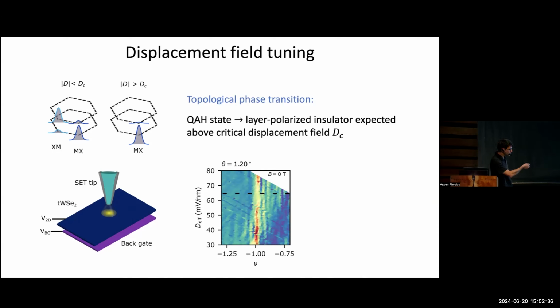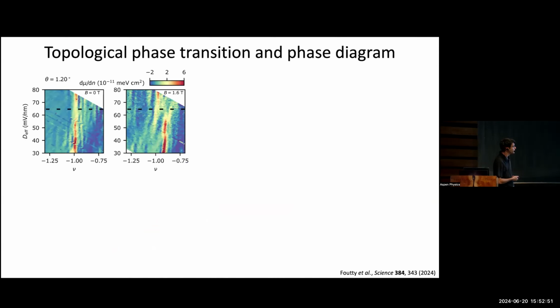So here, this is a picture at nu equals 1. As you increase the displacement field, this incompressible state gets weaker. And then past the critical field, it starts strengthening again. This sounds like the sort of displacement field-driven topological phase transition that's been predicted. We can do one better than that.